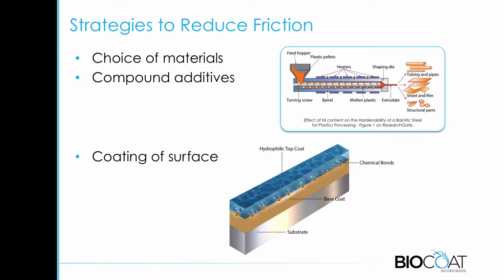And so then one way to do this is with the extruder, adding some compounding additives in there, which are sometimes waxes or other extrusion aids, which can bloom to the surface and modify, sort of lower, that surface energy, and so you've got a more slippery surface. The other final way of doing it, which is probably more near and dear to my heart, is coatings on the surface, where you're actually separating out the materials that are used structurally from the coating materials. For instance, in a Biocoat material, we put a base coat on that bonds very tenaciously to the substrate, and then from there, covalently bond our lubricious hydrophilic top coat.